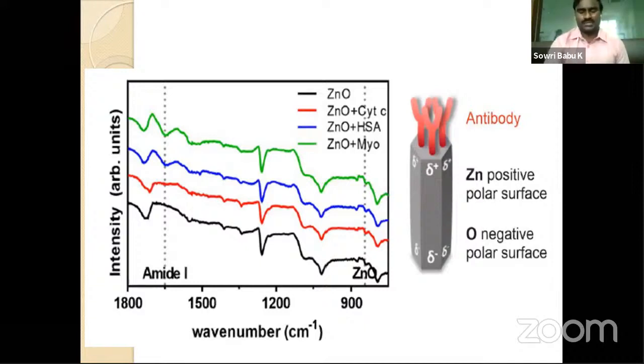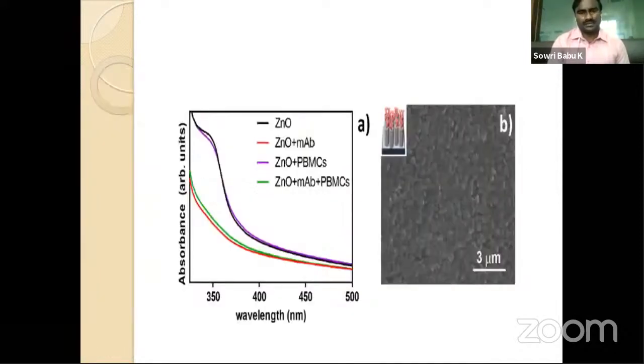Okay, so with this result, we have confirmed that they can be directly immobilized on the surface of the zinc oxide nanorod. You can see some pictures here after adding the antibodies, which are completely different from the original pictures of the zinc oxide. We have also confirmed the immobilization of monoclonal antibodies on the zinc oxide surface by using UV visible absorption.